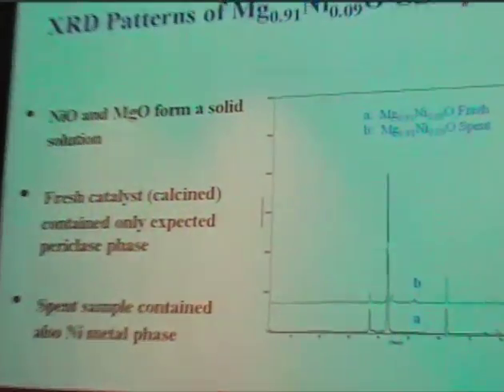So we looked at the XRD of the nickel MgO, and basically when you make the catalyst, you take nickel nitrate, wet impregnate it onto the MgO, calcine it up to 800 degrees C in the air, and then prior to putting the syngas or the feed over the catalyst, you do a pre-reduction with hydrogen for 4 hours at 800 degrees C. So that helps to activate the catalyst initially, but at the same time you'll see some TEM data where it actually reduces the nickel. But the nickel oxide and MgO is essentially a solid solution. It's infinitely soluble. They have the same face-centered cubic packing structure. So it's rather ideal for our needs here.